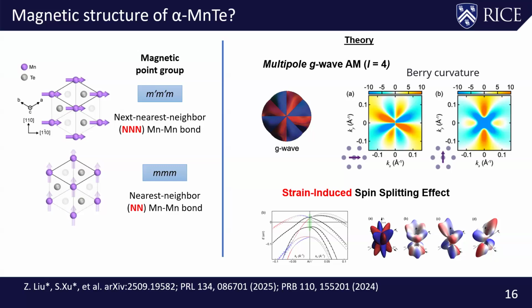But this cannot be conclusively determined, because if the moment is aligned in the AB plane, then you have three equivalent rotational symmetry directions. Because the system is ultimately hexagonal, you basically have three domains. When you add up all the intensity of the three domains, these two magnetic structures are completely equivalent. If the sample is not detwinned, you therefore cannot separate which one is correct. Of course, you can tune the system to be a d-wave altermagnet, which can directly induce anomalous Hall. But the natural tuning you would apply is about 2%. You're just going to crash the crystal before the band structure actually changes. That's what is going to happen.